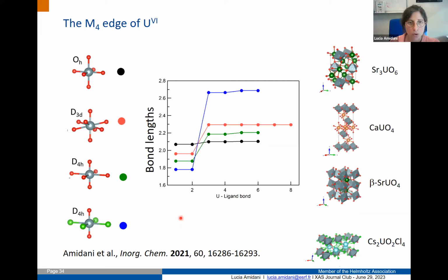This shows how the bond lengths evolve between uranium and the ligands in the first coordination shell. We go from the almost perfect octahedra, called uranate, through two intermediate cases where the bonds are lowering, to the prototypical uranyl case with 2 short and 4 longer bonds.